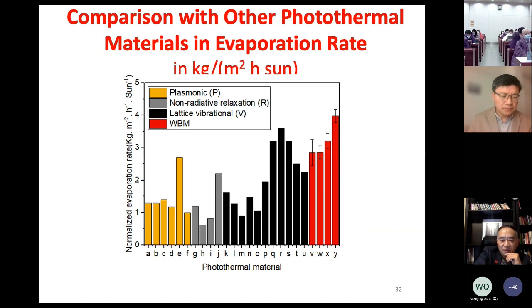The red one is from wood-based monolithic biochar, and the black one is other lattice vibrational materials, and the yellow ones are plasmonic materials, and the gray ones are non-radiative relaxation materials. What you can see here is that wood biochar are actually quite promising as photothermal materials for enhanced water evaporation.